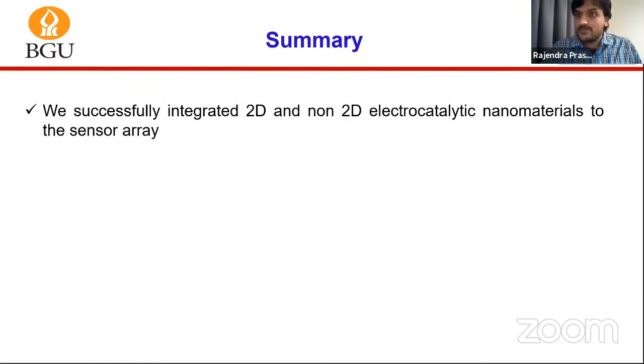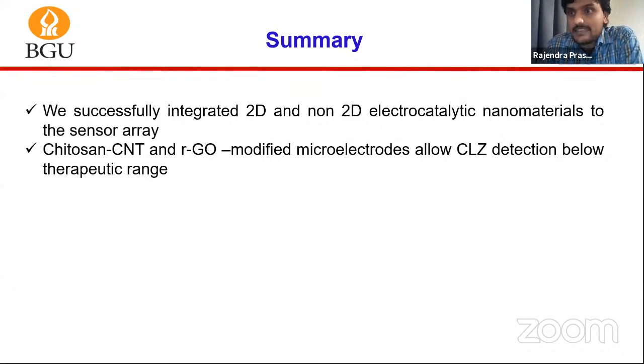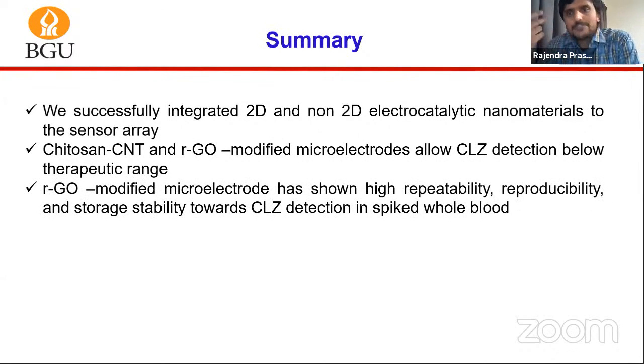So to sum up this talk, I hope I have convinced you that we have successfully integrated 2D and non-2D electrocatalytic materials into microscale electrodes. We also modified the microelectrodes with chitosan carbon nanotubes and reduced graphene oxide for the detection of clozapine. This electrode modification allows us to detect clozapine below the clinical range. Our reduced graphene oxide modified microelectrode has shown better sensing performance in terms of repeatability, reproducibility, and storage stability in spiked whole blood samples of 20 microliter volume.